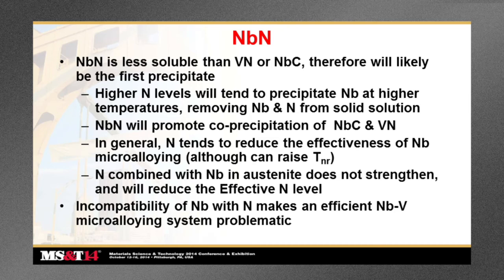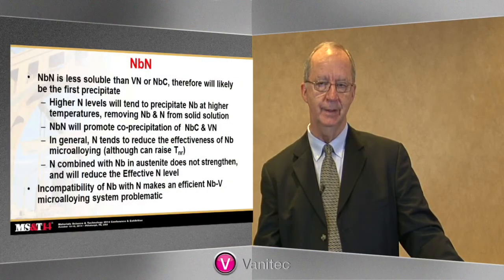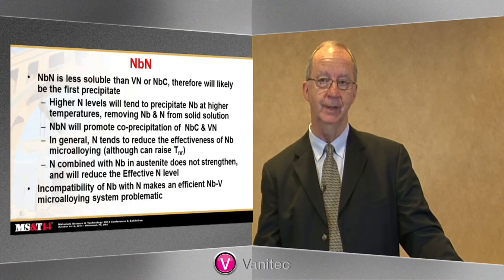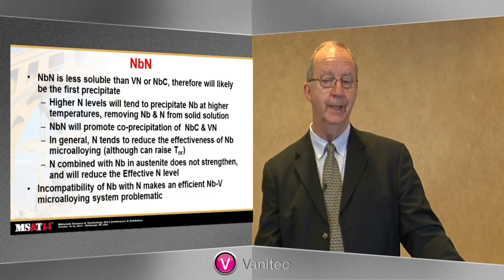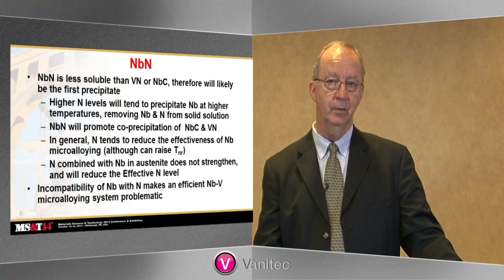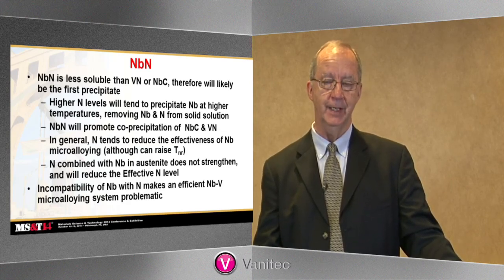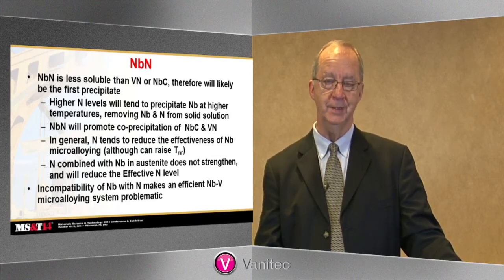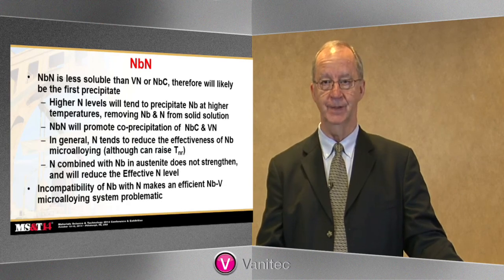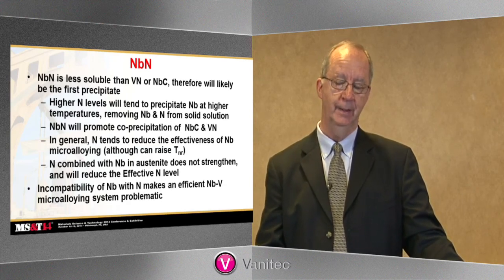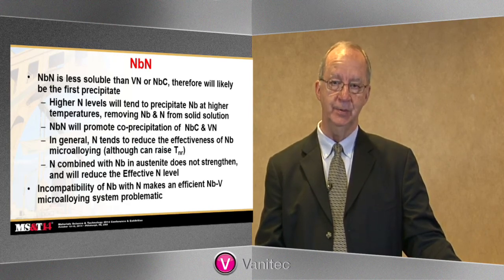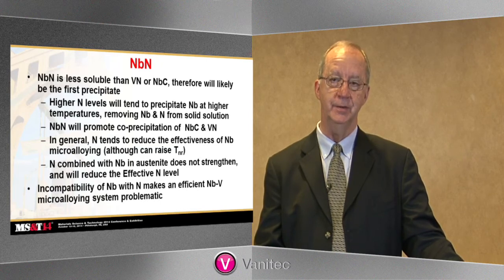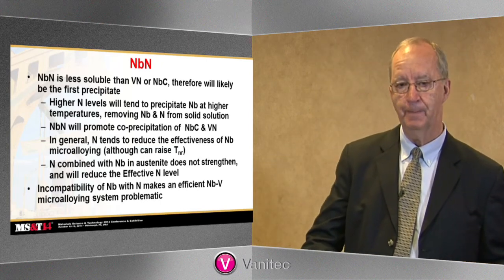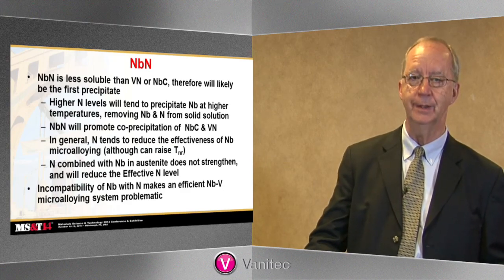And this incompatibility of niobium with nitrogen makes an efficient niobium-vanadium microalloying system somewhat problematic, because how do you use the niobium effectively and the vanadium effectively if in fact the niobium combines with the nitrogen before the vanadium, keeps it from forming vanadium nitride, which is what you want for strength. Meanwhile, the formation of niobium nitride actually reduces the effectiveness of the niobium addition in the first place as well. So this lack of synergy between the two is a major issue as we try to make these elements work together, and is something that we continue to struggle with.